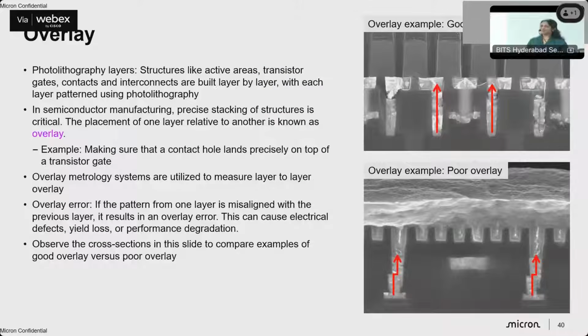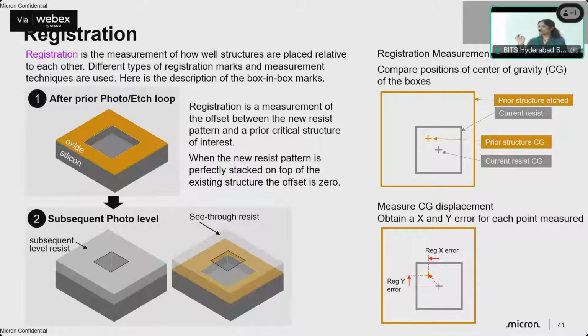Overlay. I am currently in the overlay group here. It's very important, like I said, to align whatever feature we have printed at the bottom with the top. If there is circuitry at the bottom, and at the top the via is not meeting it, then effectively you have destroyed your device. So how do you ensure that the below layer gets perfectly aligned with the top? For that, in the scribe region, which is basically the empty real estate between dies, just to saw, we use that area to place these marks at the bottom layer and at the top layer.